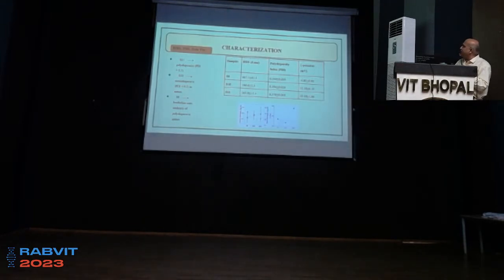And we found that only the one sample has a polydispersity index which is lesser than 0.5. That means this is the monodisperse one, whereas the other ones are a bit higher. One of the interesting points is the zeta potential, which is the potential of the particle itself, goes from negative to a little positive and it gets further positive. So it's a move towards a positive direction. By changing the pH, we have achieved some unidirectional trend along this direction.